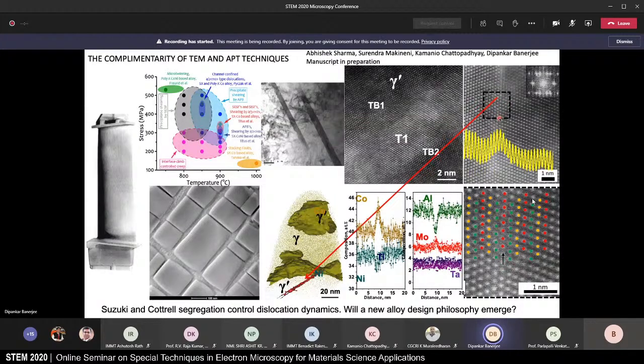However, it is very difficult to quantify energy dispersive spectroscopy, and later talks will probably look at that in more detail. So we combine this work with atom probe tomography, and you can see here, and this is the gamma phase, that is the matrix. This is the gamma prime phase over here, and this is the twin boundary within the gamma prime phase, that is this region of the TEM microstructure. And when you do that, you can see the segregation of cobalt, molybdenum, tantalum, and nickel to the twin boundaries. Okay.